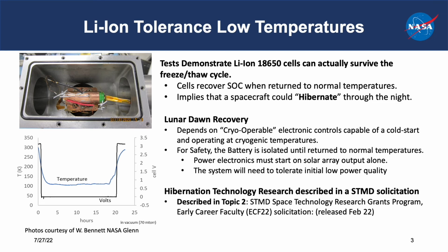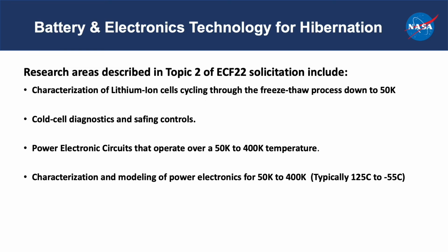But in terms of technology, hibernation technology research is described in the STMD solicitation, in Topic 2, STMD Space Technology Research Grants Program Early Career Faculty. That was released back in February 22. So research areas described in Topic 2 of the ECF 22 solicitation include the following: the characterization of lithium-ion cells cycling through the freeze-thaw process down to 50 K. The rationale is that little is known about the transition between normal and frozen states within the lithium-ion cells.